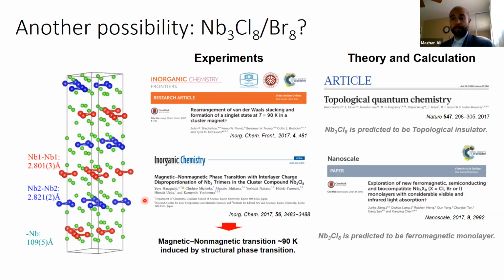So at low temperature, it looks to be non-magnetic. And it was predicted by Bernevig and friends to be a topological insulator, actually. It does not appear to be, but it was proposed that maybe it could be, depending on the correlation strength. And in the monolayer, other people predicted that it should be one of these 2D ferromagnets. So it's an interesting material and family to go hunting around in.